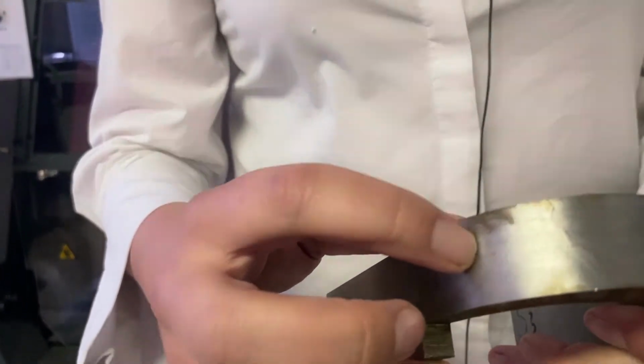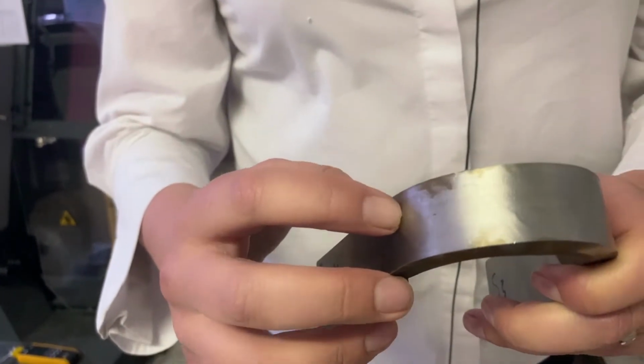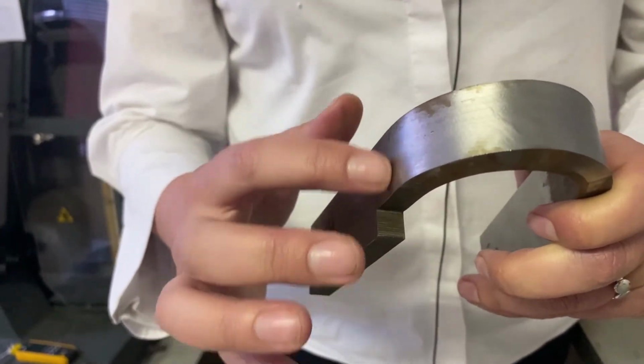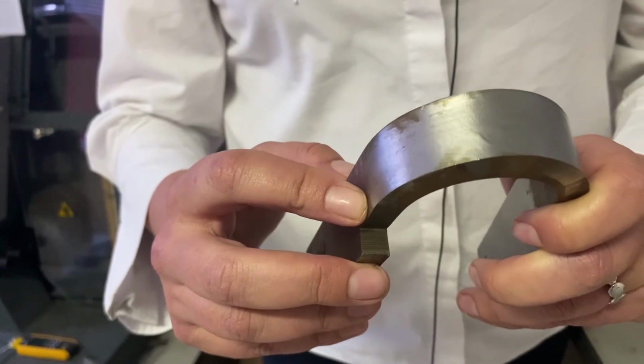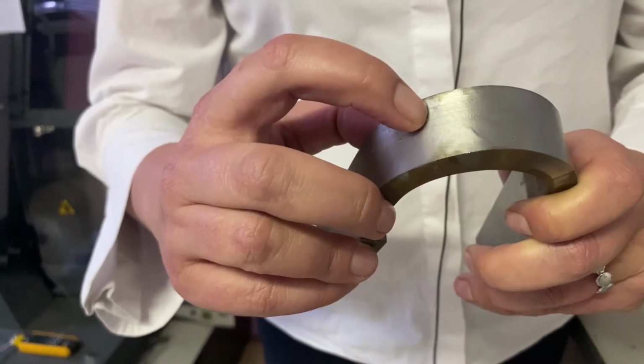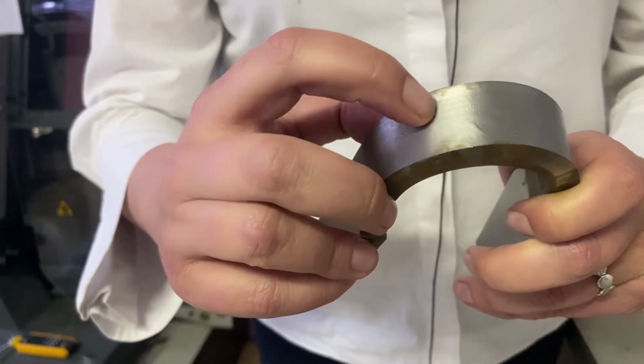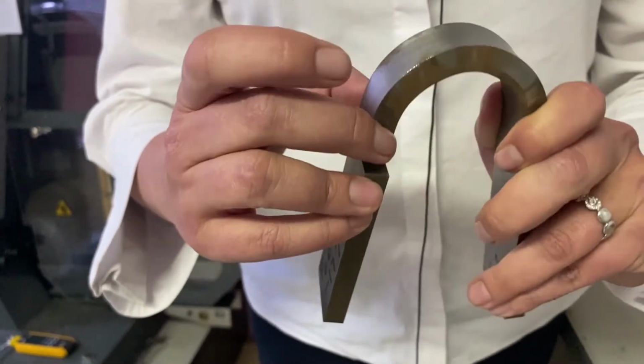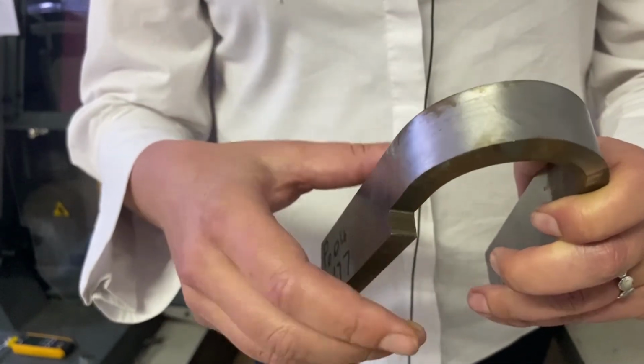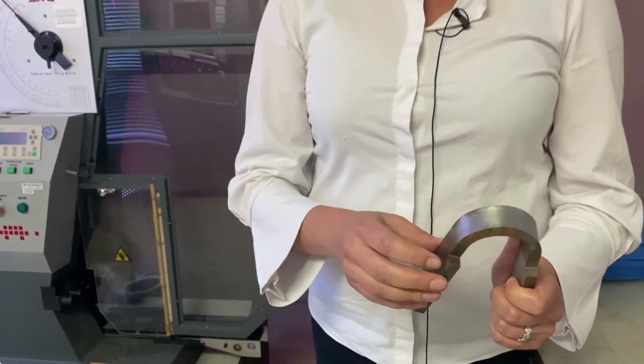So if you have a look over here, the purpose of this test is to evaluate the welded joint that you see over there. If the sample is not machined to the correct surface finish, it will be impossible to detect any flaws in the welded joint after the bend test is completed. And that can mean that if the surface finish is not appropriate, that a welding procedure qualification could pass when in fact it should have failed. And that will mean only catastrophic results if the welding is conducted according to a weld procedure that should have not passed.